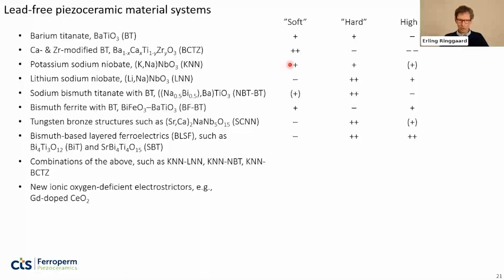Okay, KNN is a quite well-known lead-free alternative. It can be doped both for soft and hard properties. In terms of temperature, it's a fairly high temperature material. Some variants can be used at higher temperatures than PZT. There are also quite a few that are intended for a bit lower temperatures, around 200 degrees, but that depends on the composition. But quite a versatile lead-free alternative. As you see, you have pluses all over here. Then a related material, lithium sodium niobate, in this case with a high content of lithium. For example, for single crystals, you can get very hard properties, and this is also useful for high temperatures, but generally not soft characteristics.